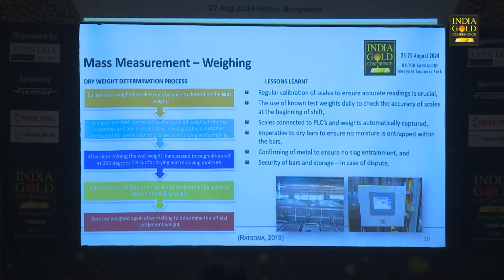So a quick one, what are the lessons that you've learned from weighing? I think one of the things is that in the mining process, samples are quenched in water. They are dipped before the bars come to us. So for us, it is important to dry those samples to make sure that we don't pay for moisture. So we dry it at 350 degrees, whereby because of that 17025 accreditation that I've mentioned on quality, we make sure that the ovens that we do use are the latest and they dry to consistent weight before the weight is pronounced.